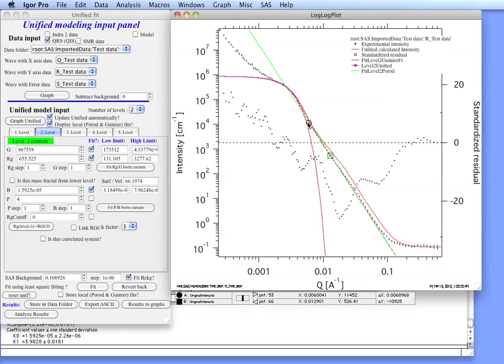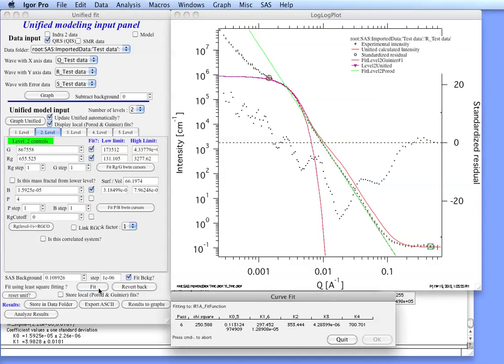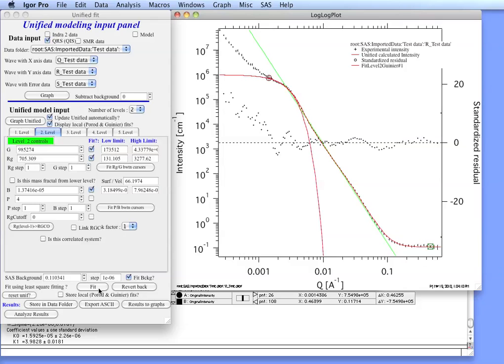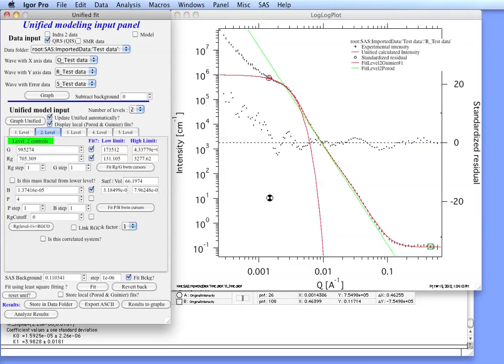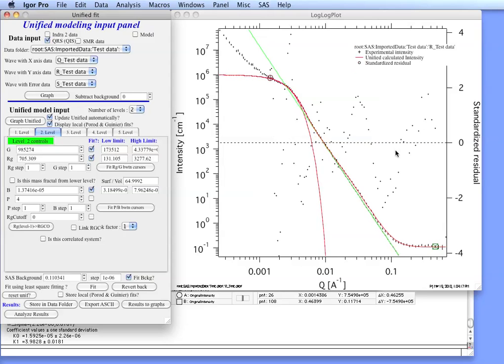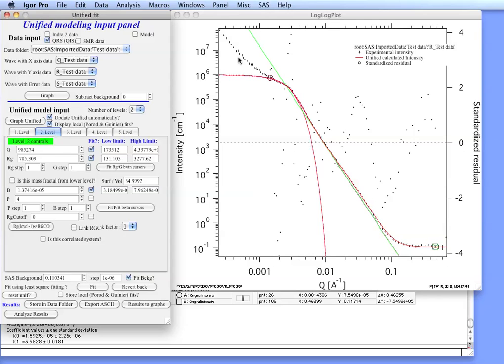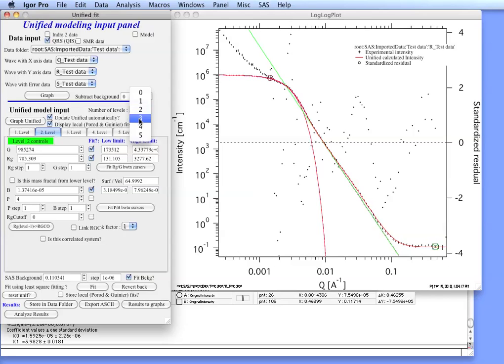Now with this we can now select a whole range of the data all the way and now do a fit on the data all together. You can see that we fit very nicely these data. The normalized residual is actually pretty good. Next what we need to decide is what is this low Q power law slope. Since this has been a mixture of two powders, it's possibly either some kind of large powders or more likely some of the powders actually agglomerate together and create larger particles. Let's assume this would be agglomeration of the particles with this size here. So what we want to do is model this. But because you don't see the Guinier area for this, you just see the power law slope, you have a limited amount of data available to you. So what we do is we will actually add one more level in this case, level 3. And click on the level 3 tab.